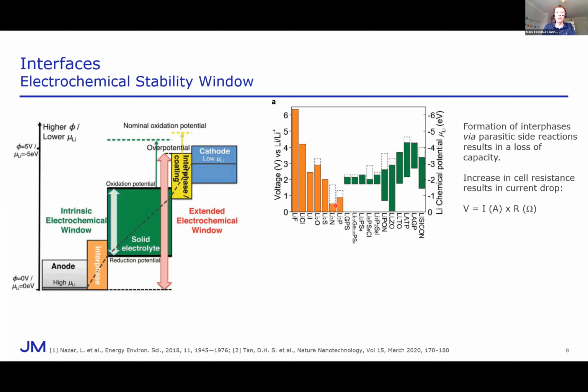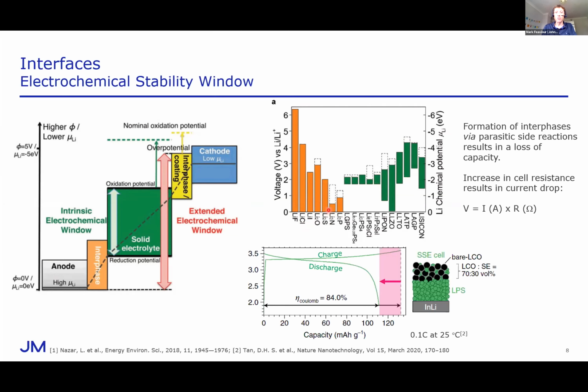The formation of these materials actually can be observed in test data, because these reactions consume lithium. They're so-called parasitic reactions. So this is just typical test data. You charge it up to a certain voltage corresponding to a capacity, and then you discharge it, and you don't achieve the same capacity back out of the battery. That represents a loss in lithium, because that lithium has been reacted to make some of these interphase compounds. And if they're stable, you can form a self-passivating layer, and this will stabilize. If that doesn't stabilize, because perhaps it's electronically conductive, then eventually it all breaks down.